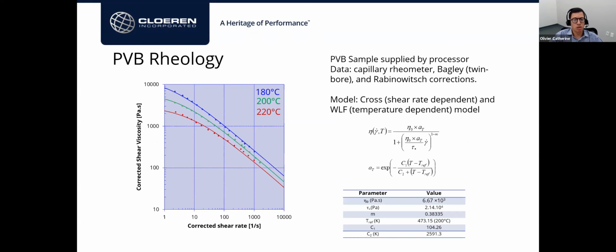So this is PVB, polyvinyl butyral, and we measured this material quite well with our capillary rheometer in the lab at 3 different temperatures. You can see very nice measurements. We are able to fit the data quite well with a classic Cross model using a WLF temperature dependency. Here are all the parameters. You can see the curve fit is quite nice, right?